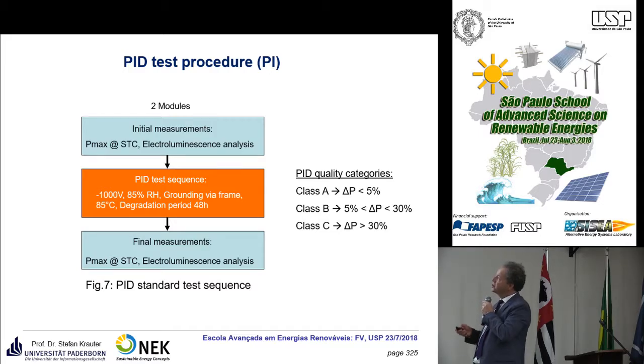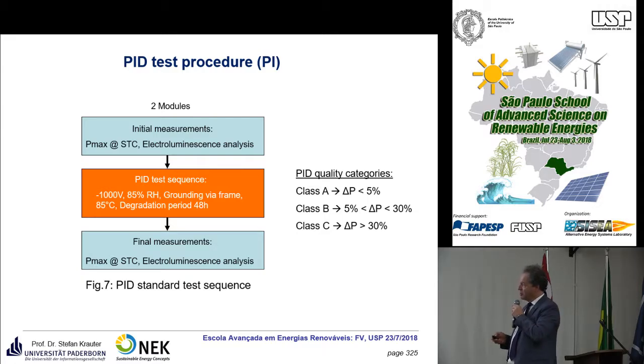So we have a test procedure to do that. So we do electroluminescence analysis. We keep it at minus 1000 volts for 48 hours, and then we perform a power output measurement again. And so we classify the modules. Class A, where the power drop is less than 5%, and Class C, where the power drop is more than 30%, and Class B in the middle.